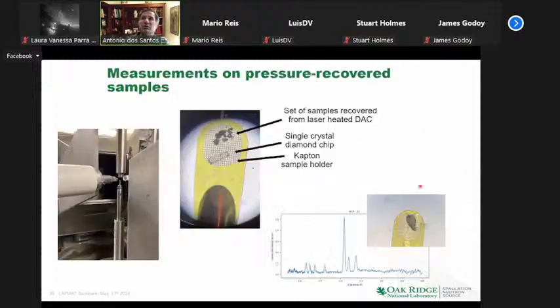Another thing we want to do is use the lessons learned from using such small beams to then measure really small pressure-recovered samples or other rare materials. So these are samples recovered from a laser heated DAC, and this was a single crystal diamond chip that would help us know that we are really shining on the right spot. This little holder is only about 600 microns in diameter. This is technetium, which is an unstable isotope, so you really don't want to handle a lot of it. And this is the powder pattern of this small piece of technetium in our beamlines.